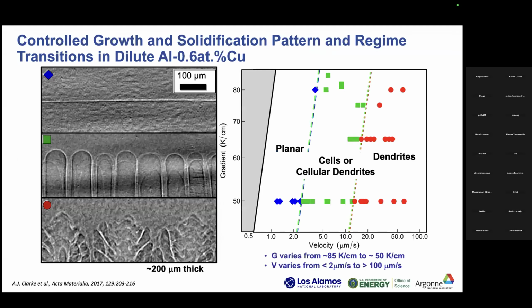So one of the first sets of experiments we did, these are again examples from 200 micron thick foils of aluminum copper, a very dilute aluminum copper alloy, is we actually mapped out this processing space in real time, the G and V combinations that give us the different growth regimes and the growth regime transitions. So shown over here on the one side is an example of the different interfaces we can generate in the solidification patterns. So we can have a planar solid-liquid interface, these cell-like structures or hierarchical type dendrite structures. And then on the other side is an example of GV mapping we kind of did in real time.